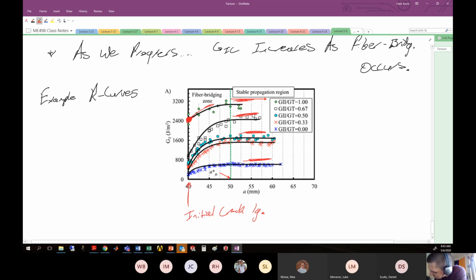where this plateau occurs when the amount of fibers that you're creating in your fiber bridging region is equal to the amount that have been lost from the back end of the testing. All right, so let's say you have 10 fibers that are holding on as you propagate your crack. If I propagate my crack a little bit more such that one more fiber is holding on and I lose one from the other end, then I'm keeping this equilibrium of only 10 fibers bridging my crack plane at any time. But when I first start, I have 0 fibers bridging the crack. And then as it propagates, I accumulate 1, 2, 3, 4, 5, 6, 7, 8, 9, 10 until at the very front, I've reached this equilibrium where I only have 10 fibers that are holding. Obviously it's a lot more than 10, but I'm just trying to make an example here.